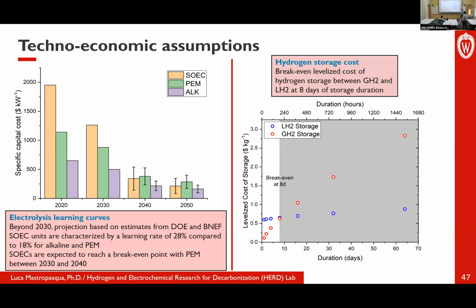So I guess alkaline and PEM are considerably cheaper than SOEC, and they're more commercially used, but they're less efficient, right? Yeah. So what makes SOEC significantly more efficient is just the addition of heat? Yeah, so if you work at high temperature, the kinetics are a lot faster than at a low, ambient temperature. And that gives the higher efficiency to SOEC.